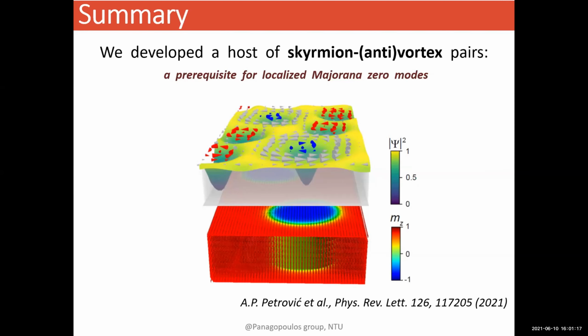So I want to just ask, how did you measure chiral magnetic moment? Because you have written microjoule per Tesla. So this is an estimate from ferromagnetic resonance together with simulations. We have different methods, and not all of them are direct. So we do simulations, we do also transport measurements, magnetization measurements, and also imaging as well, which we try to fit very often with calculations or micromagnetic simulations in order to get quantitative estimates.